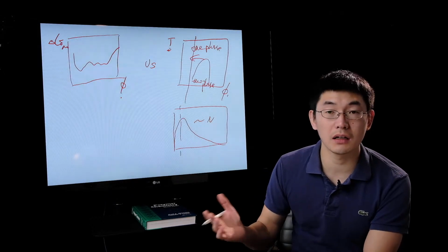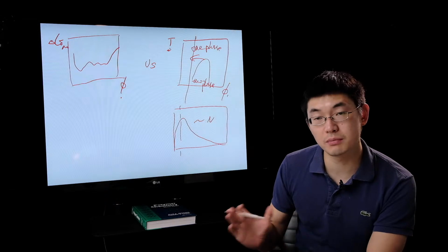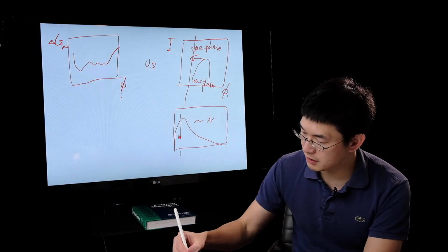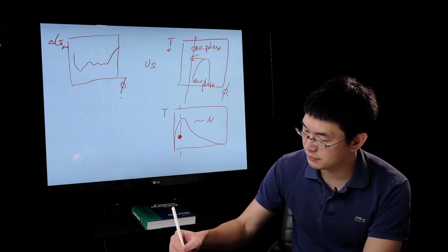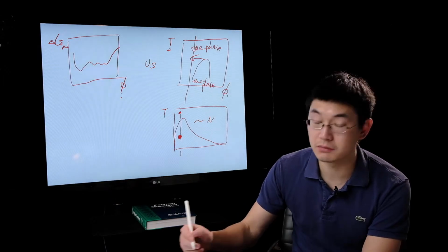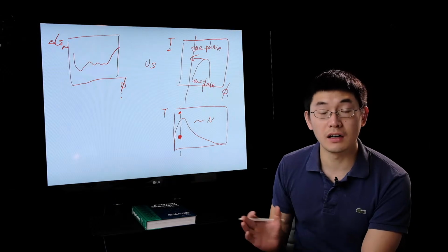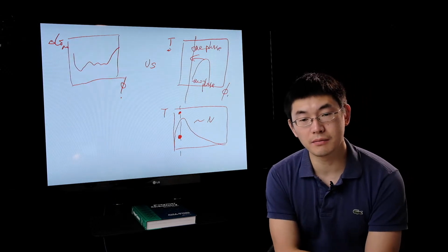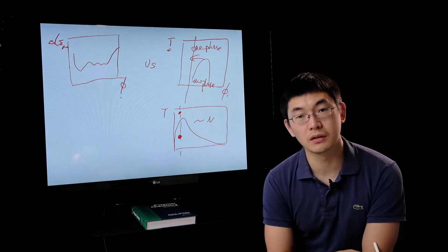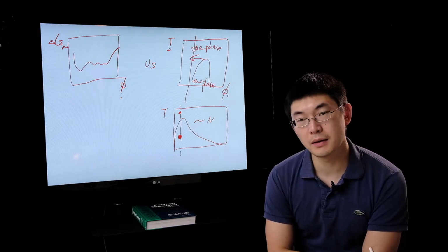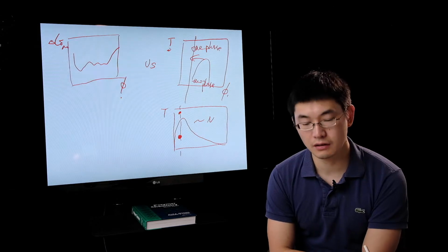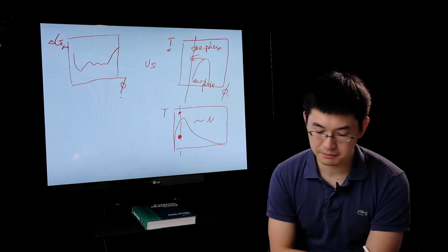If you look at the polymer dissolved in toluene, this polymer X, then you might be able to see that at low temperature it will sit in the two phase, but if you increase the temperature, it will sit in the one phase. So I can get knowledge about what processing condition I need to take in terms of mixing for preparing a solution. Okay, that would be a great example.